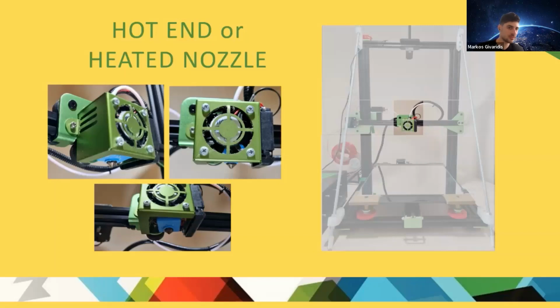In my opinion, the hotend is a very critical component of a 3D printer, and issues in this area can have very significant effects on the final print. The most common issue, for example, is the clog of the hotend, which can lead to incorrect extrusion or no extrusion at all. A common cause of clogs is heat creep, where heat climbs behind the melt zone, and the material melts too early, blocking the filament path.